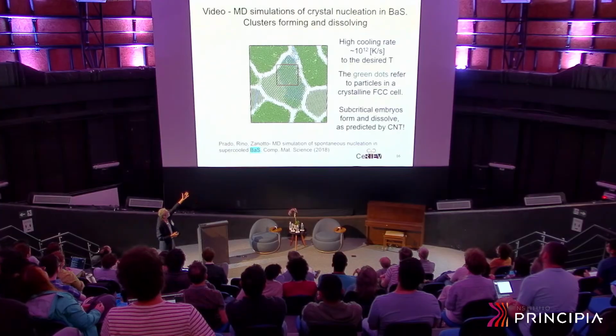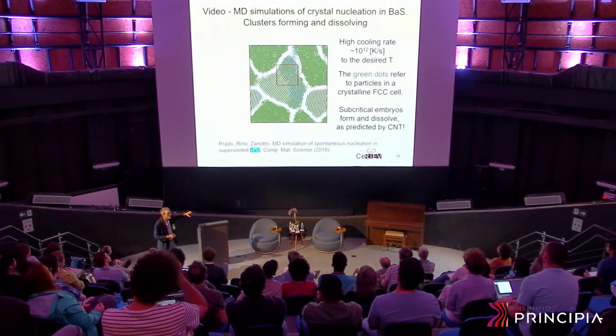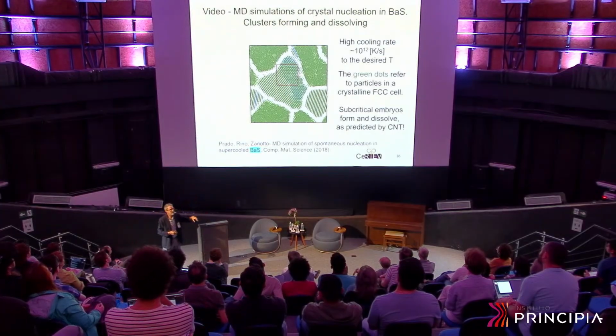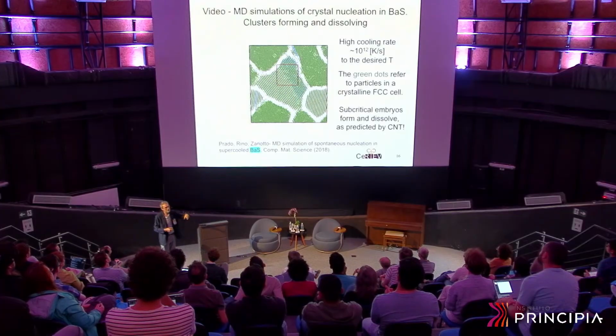And if you can do that by MD simulations, you can compute the time to form the first nucleus at different temperatures. And then you can calculate nucleation rates.